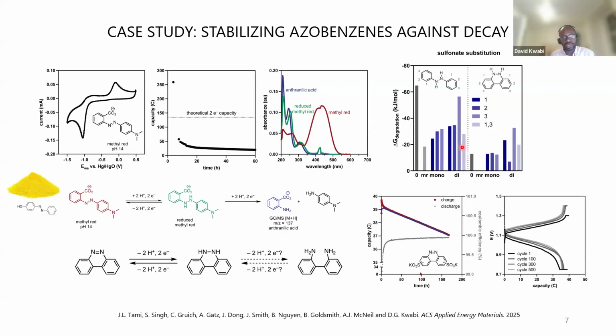We were very encouraged by these results, and we synthesized this new scaffold and found that our degradation rate was tremendously slowed. So we are going from losing about 80+% of our capacity in about a day to losing about 0.1, 0.3% per day with this new scaffold, which was very encouraging. So this gives you a sense of how our workflow operates, where we can take one molecule, understand how it degrades, and using that information, we can design more resilient systems.